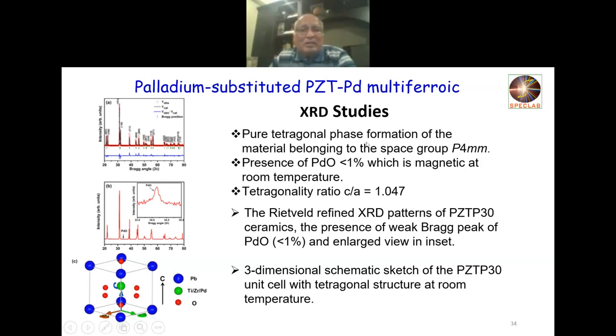Here we see actually pure tetragonal phase formation of the material. The resultant material was indeed still pure tetragonal phase, the space group was 4mm, and the tetragonality ratio was 1.047 here. In the XRD studies, the presence of weak Bragg peaks was observed for Pd oxides, very weak. So for the rest, the material had a single phase.